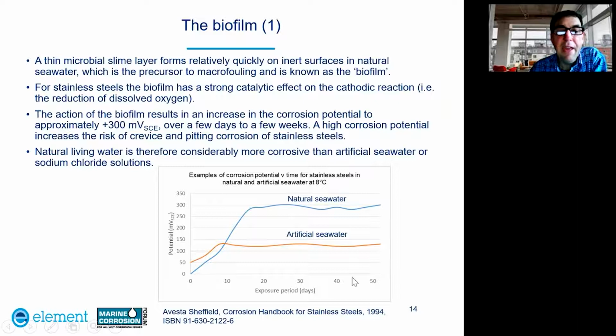So this graph here shows the effect of the biofilm on stainless steels in natural seawater, where they'd follow this path where the potential would increase to around about the 300 millivolt region, whereas in artificial seawater you get a small increase but not a significant increase in this potential. So the result of this ennoblement of the stainless steels is that natural living water is therefore considerably more corrosive than artificial seawater or sodium chloride solutions.